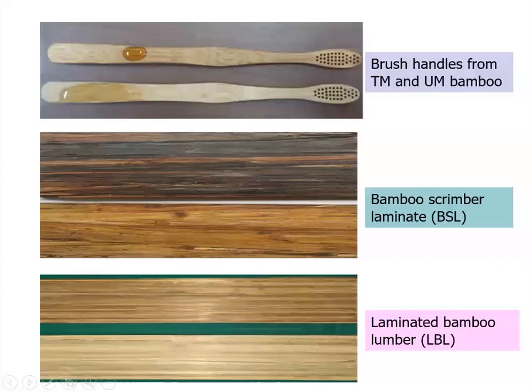The main difficulty for bamboo flattening is the difference of circumference between the inner and outer layer of the bamboo, because of the difference in inner diameter and outer diameter, and the low tangential tensile strength of the inner layer. The inner layer has low tensile strength compared to the outer layer. The outer layer is the strongest layer in the bamboo. Because of that, there are difficulties in flattening the bamboo, but it can be flattened using certain techniques. Flattening can be done by a thermomechanical process, and then it can be cut and glued into different bamboo products. So flattening can overcome the cylindrical shape of the bamboo, consequently diversifying bamboo applications.